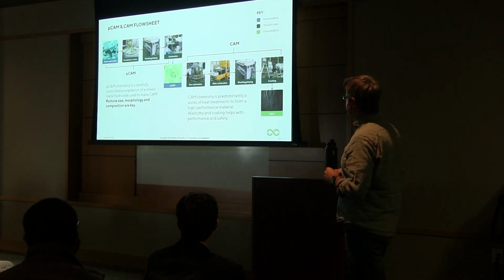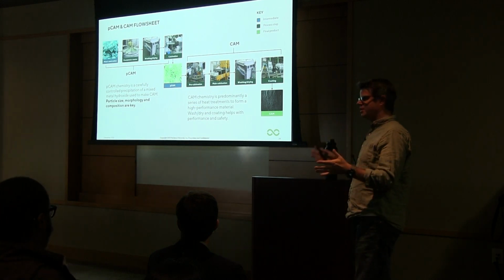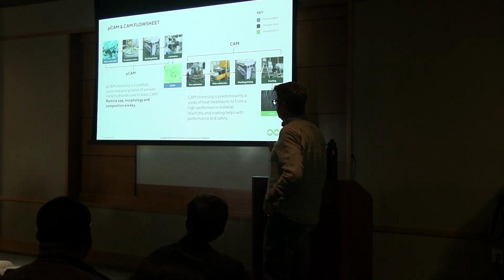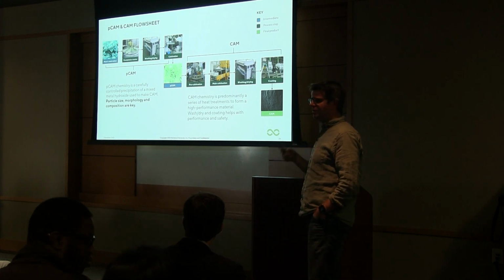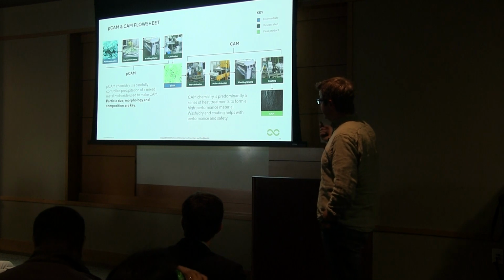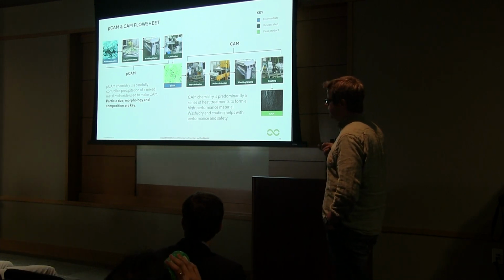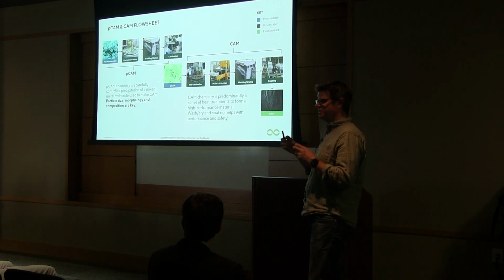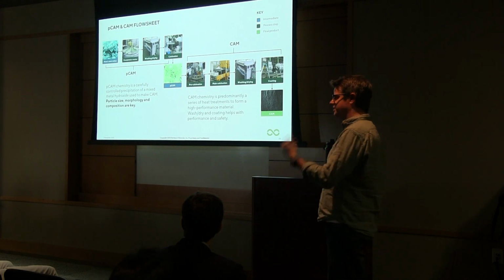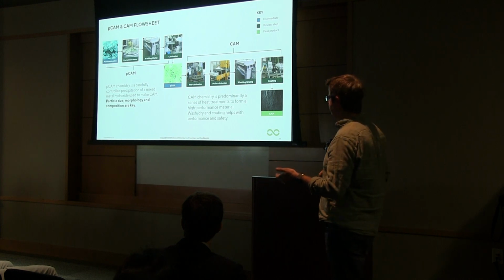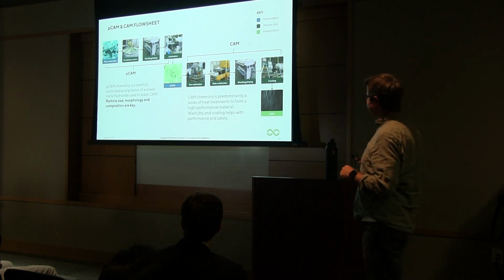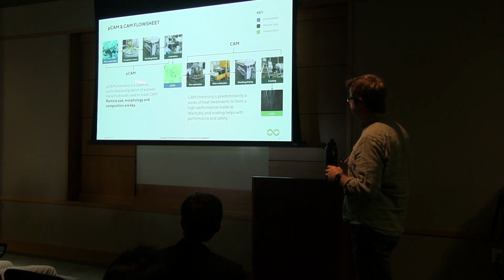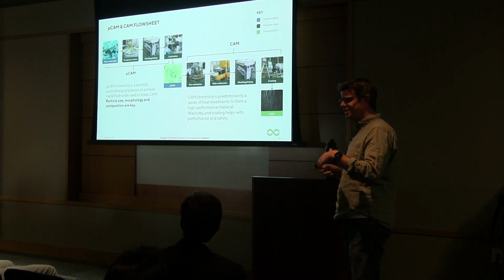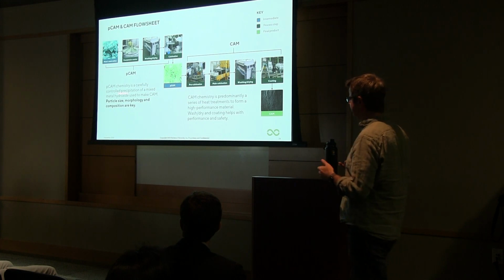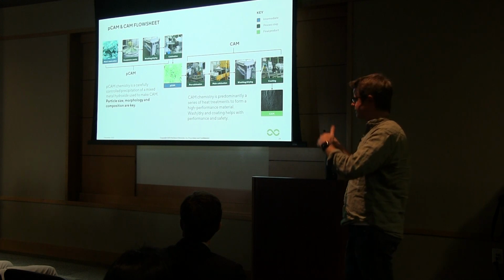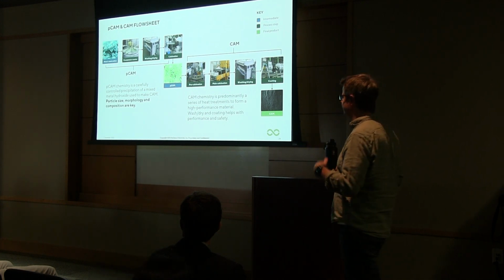Okay, on to cathode active material. When we're making cathode active material, it's made in primarily 2 steps. The first thing that we take is mixed sulfate metals. So this is going to be nickel, cobalt, a little bit of aluminum. And what we're trying to do is go from these nickel sulfates and cobalt sulfates into hydroxides. We mix the sulfates in a very specific ratio to each other. We precipitate it with sodium hydroxide, also some ammonium hydroxide, to produce a metal hydroxide, and that's called PCAM. The way you precipitate it is in very high-powered, high-sheared, agitated reactors. There's a very specific particle size and morphology, key to this in terms of how all the metals lock together. But this is really just your nickel, cobalt, aluminum, manganese.